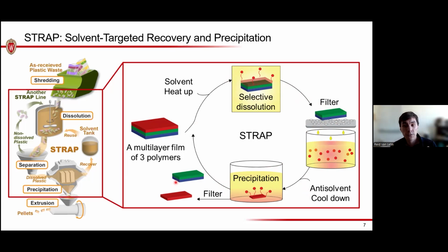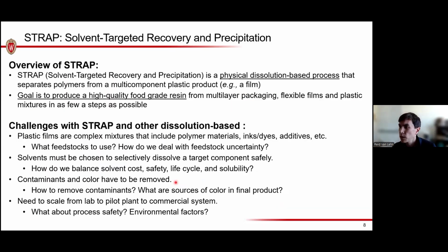So again, unlike the advanced recycling techniques or pyrolysis that we just heard about, there's no chemical transformation of the polymer here. This is more like a physical dissolution process, okay? So that's the basic idea. This allows us to separate polymers from a multi-component plastic product like a film, or in general, mixed plastic waste. So any plastic mixture in principle could be treated with this type of material. And the idea is that because we're not going back to monomer, if we do this right and we get a high quality plastic material out, it can immediately be reused for whatever the original application was without having to go back through the polymerization process.